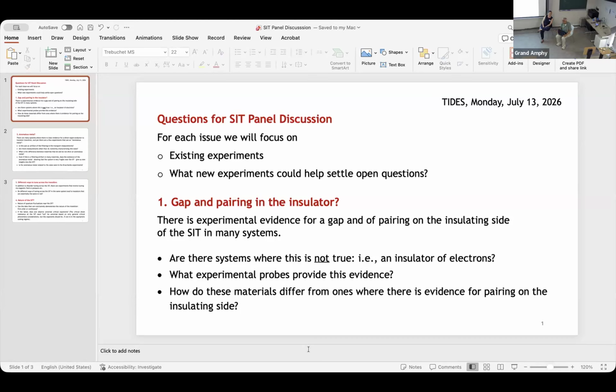Spatial resolution. So the problem is that you always collect, if they correlate, you can't limit it. The size of the probe is not the limiting factor. It's the cloud. We did that with a very, very low superfluid in the Josephson junction arrays. And we see that the moment the superfluid is very weak, we actually sense a larger area than we think. So it actually goes larger in space the weaker it is, and the clouds that we see extend way bigger than the probe.